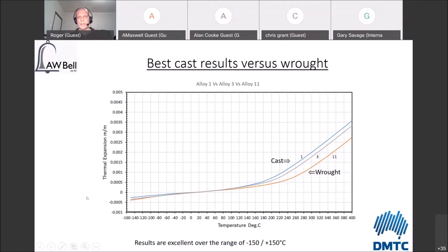So that was a very, very encouraging result, definitely. And now the offset in the wrought material off to the right-hand side, we believe we knew why that was, and we proved it later on. Basically, it's simply that the wrought material had a higher nickel content. So it had around about 38% nickel. We were working around 36%.